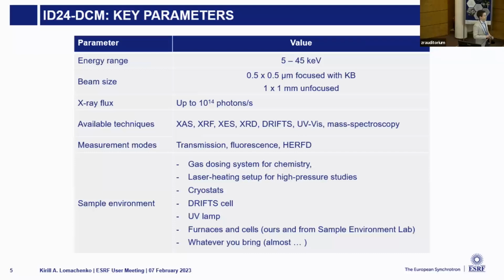So a little bit more in detail about ID24 DCM. The energy range spans from 5 to 45 kiloelectron volts, so basically all relevant hard X-ray regions are covered. The beam size can be focused down to around half by half micron, but it can also be unfocused to roughly 1 by 1 millimeter if you don't need focusing but want to preserve your sample a little bit. X-ray flux is very high thanks to the 3 undulators that we have. Available techniques are numerous. The core business is XAS, but we can also do XRF, XES, XRD, DRIFTS, UV-vis, and many more. We can measure in transmission and fluorescence and in high resolution fluorescence mode.